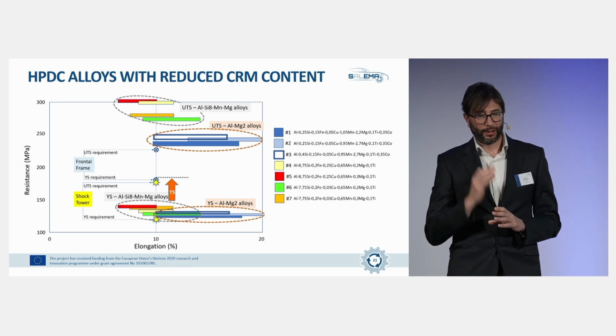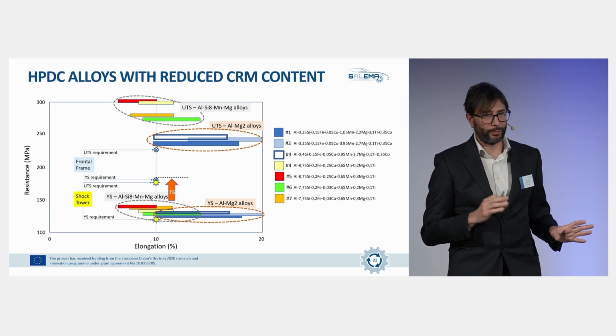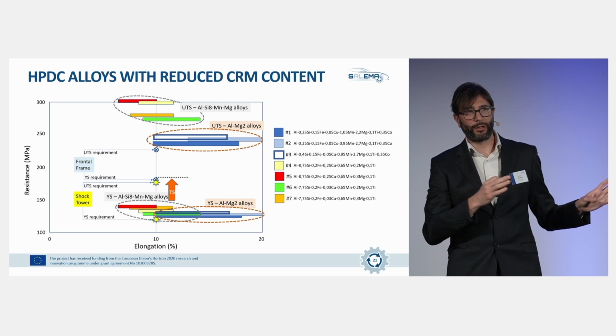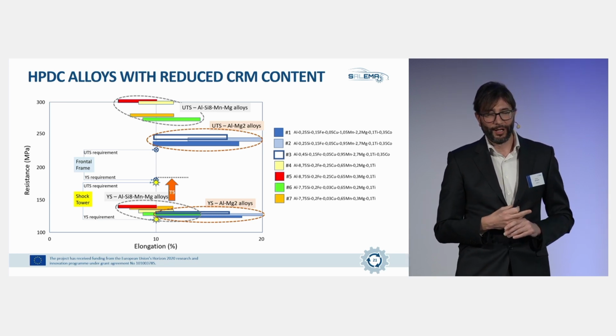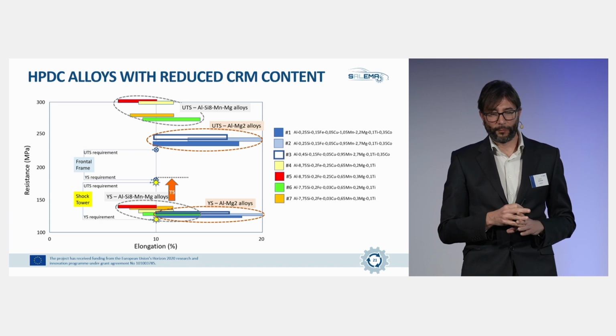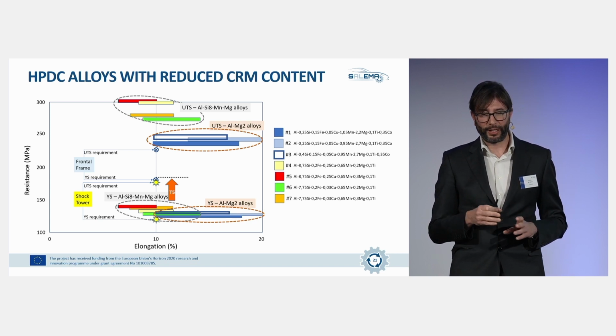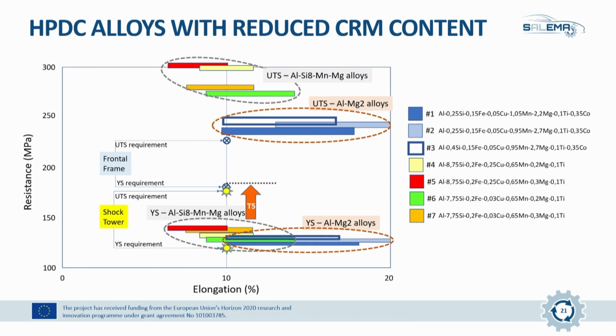So we select 3 alloy variants for the aluminium magnesium 2 family. That was one quite good scoring family, and 4 variants for aluminium silicon 8 manganese magnesium alloys. Parts were produced by high pressure die casting, and then the mechanical properties were determined for those parts. And again, without heat treatment, the yield strength and the UTS requirements for the shock tower could be met.